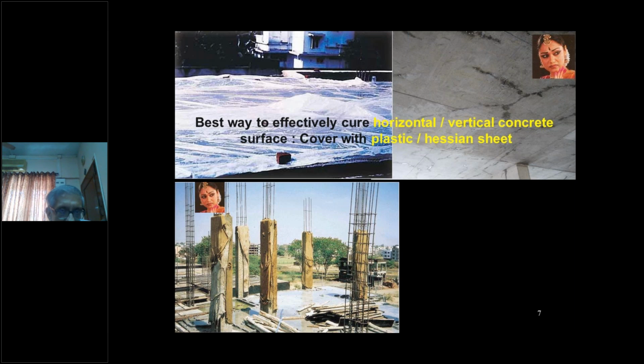On the left hand side lower slide, you can see people covering the vertical faces of freshly cast columns with Hessian cloth. Now, the reason I am not recommending Hessian cloth on top of the slab is because Hessian is porous. You have to keep it wet throughout so that water will not dry out from the Hessian cloth. Whereas plastic does not allow the water to leave. You can see the humidity between the plastic sheet and the slab, just like when you wear a shirt and you are perspiring, it looks wet and maintains the coolness of your body. This also does not allow further evaporation from the concrete.